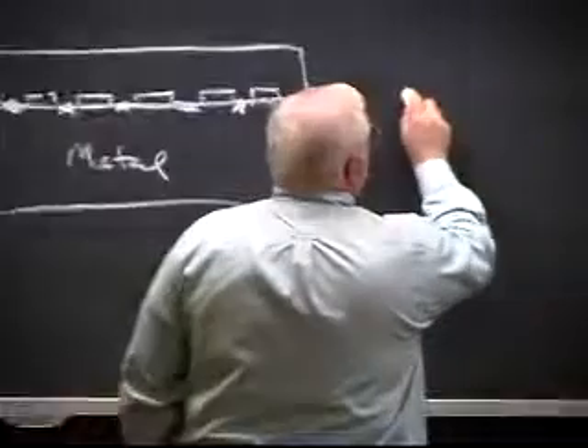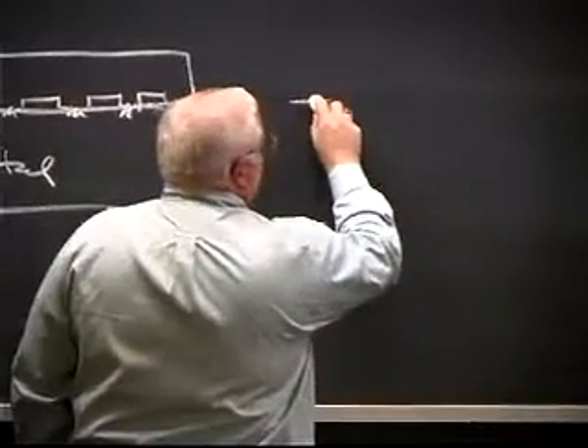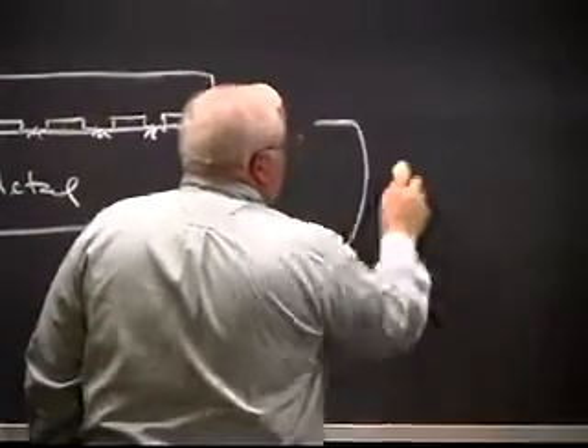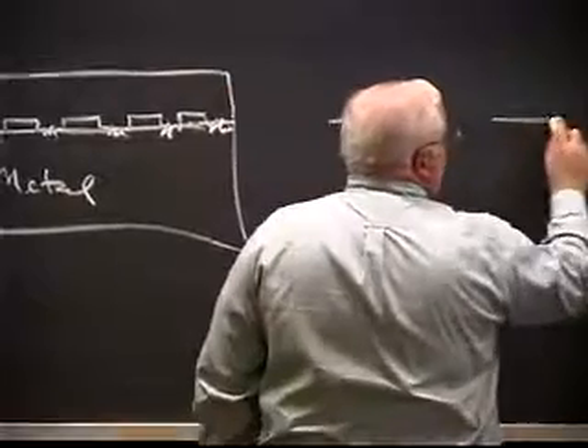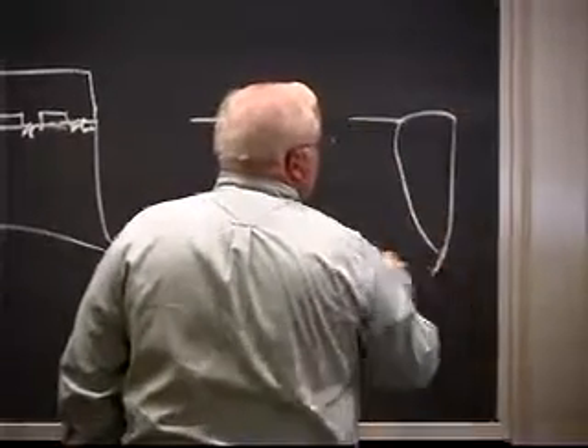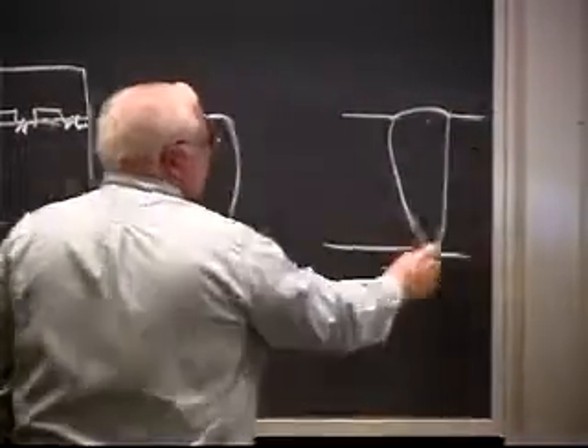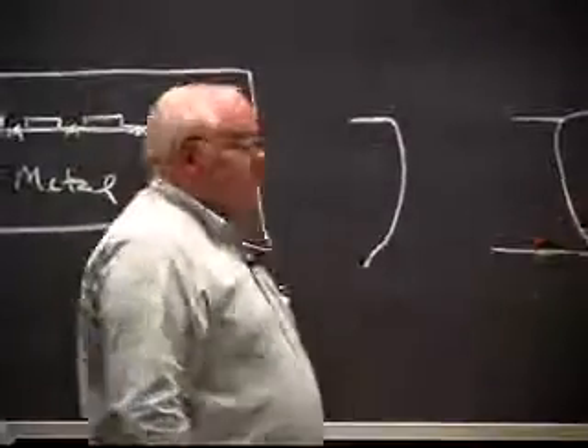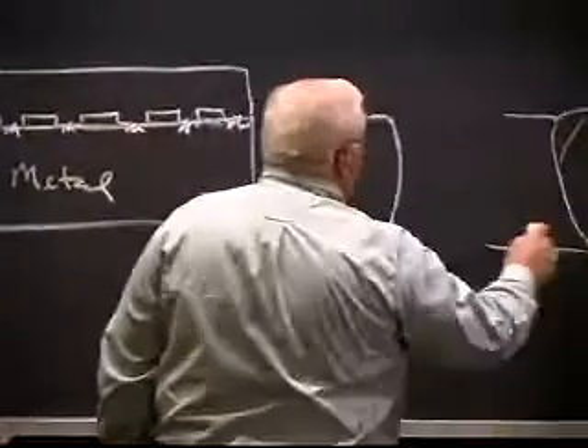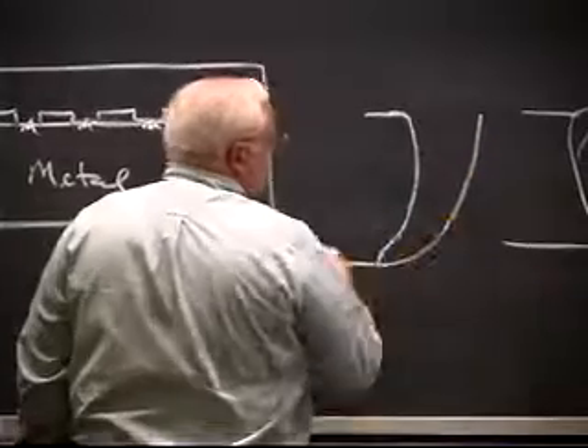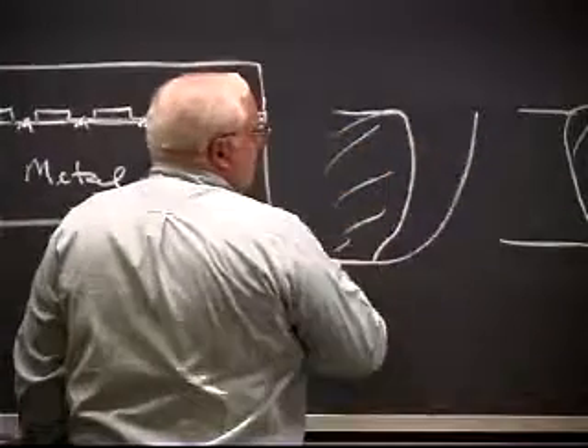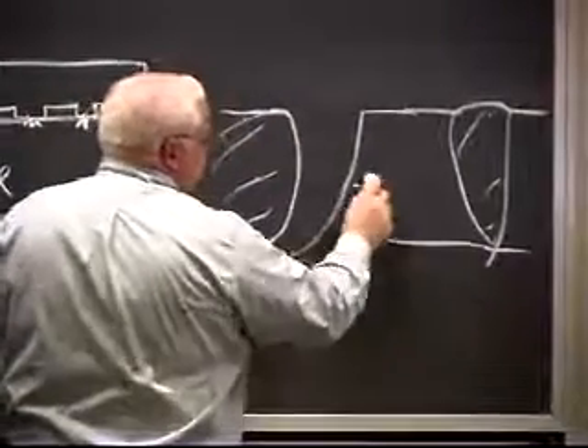They do things with lasers and electron beam so you can see the fluid flow that's going on. In laser and electron beam, you get a very deep weld pool. You have something on the order of 1,000,000 watts per square centimeter, and you will get, in cross-section, looking at the finished weld, something that's 5 or 10 times as deep as it is wide. Okay, an aspect ratio, so the weld bead looks something like this. And it does that looking on sideways view. This is your weld metal that's solidified down here. This is the material you're traveling in that direction.